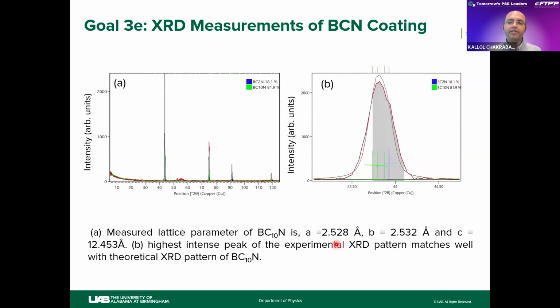Then we did the X-ray diffraction of our synthesized coating, and it matches well with the theoretically predicted XRD pattern by Dr. Chan's group. When we did the Rietveld refinement, it confirms that our coating has around 82% of BC10N and 18% of BC2N.